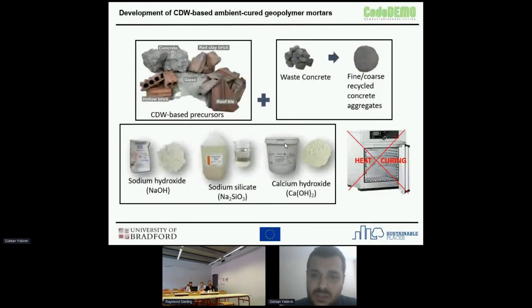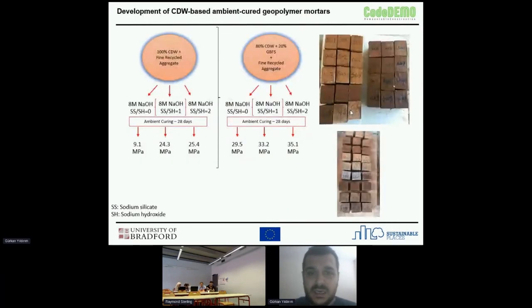So what we wanted in the following step was to get rid of heat curing, and we tried different alkaline activators to do that. We were using sodium hydroxide at the beginning, then we combined sodium hydroxide with different alkaline activators such as sodium silicate and calcium hydroxide in different proportions, and then we incorporated the CDW-based precursors or source materials and geopolymers with fine and coarse recycled aggregates coming from waste concrete. So in the end, what we are left with is a concrete material made out of completely construction and demolition waste. This is the following step. This is where we are at the moment, and we are currently working on developing concrete mixtures with coarser aggregates.